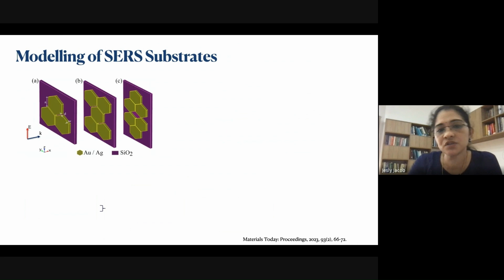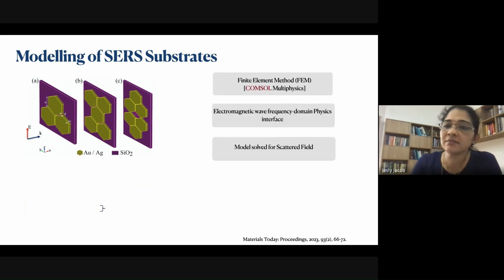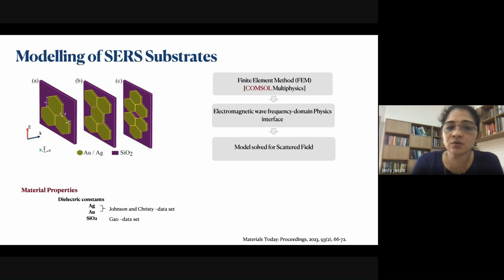So we are theoretically modeling the SERS substrates, and the substrate which is discussed in this work is a hexagonal nano disk of silver or gold. It is on the base of silicon dioxide, and we have taken a trimer structure and improvised this into some arrays of pentamers and hexamers. And we have used the finite element method using COMSOL Multiphysics, solved using the electromagnetic frequency domain and scattered field. So the material parameters for gold and silver are chosen from the Johnson and Christy data, and silicon dioxide from Gao et al.